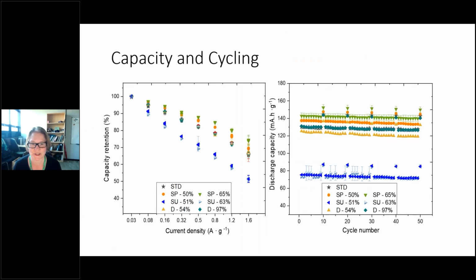And what we did here was show that the level of impurities that we got in those materials waste streams made a huge difference in terms of our specific capacities of our reclaimed and remanufactured cathodes. So it didn't matter whether you reclaimed your materials from a disassembly route or a shredded route. What mattered was the impurity concentration. And if you could remove those impurities, then you could get your cathodes to perform very similarly to what you would expect a pristine cathode that you would purchase to manufacture as well.